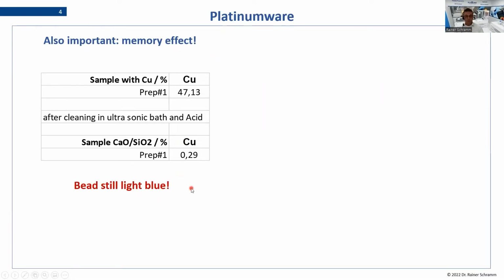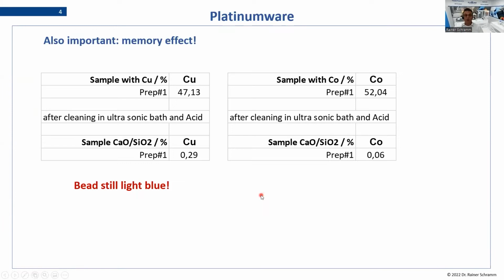But very often you can see when you make a blank afterwards that even the blank is still blue, and so you see the copper by your eyes. You don't need an X-ray instrument. For comparison, if we look at cobalt, there it's a bit different. Same concentration range, but only a small contamination we see in the next sample. So copper is really the most serious case. The other elements like iron, nickel, zinc, they also show this, but on a very low level. But be careful when you have high concentration elements, and you have to expect some cross-contamination there.